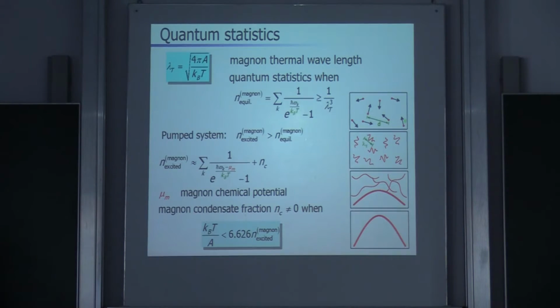Now, the interesting thing is that if this chemical potential approaches the band gap of the magnons, that is this omega 0, then even this distribution cannot take care of all the magnon states, and then we get something which is a condensate. So a magnon condensate is a coherent state of the magnons at the minimum energy of the system. Now, you can get a criterion for that if you assume that the magnons are non-interacting.